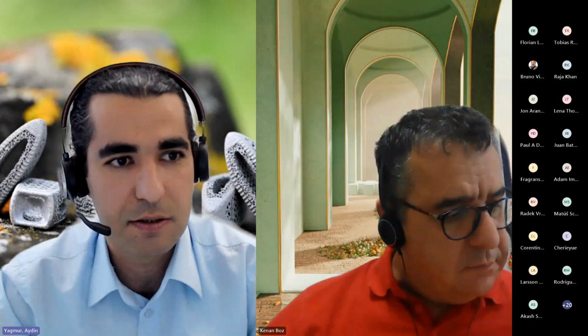And the HIPping methods, HIPping recipes are mostly from the casting industry. For different parts of material property, there are different origins of defects, and also the scales are different. So HIPping is, yes, closing some porosities, but at the same time has a risk of deteriorating the mechanical properties. So this is maybe the first remark from my side.